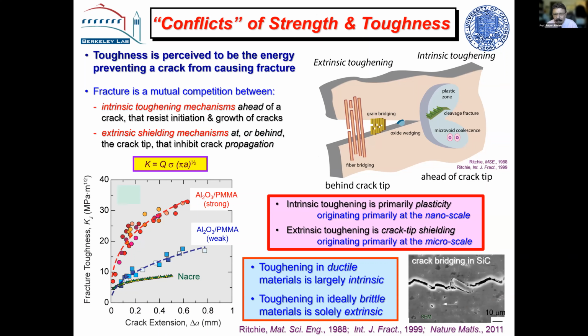It's obviously perceived to be the energy preventing a crack from causing fracture. But I look at it as a competition. And it's a competition between two classes of toughening mechanisms. The classic ones, which are the ones that are primarily used in ductile materials, I call intrinsic toughening mechanisms. They take place ahead of a crack tip, and they are basically mechanisms that inhibit damage. And the primary driver for this is plasticity.